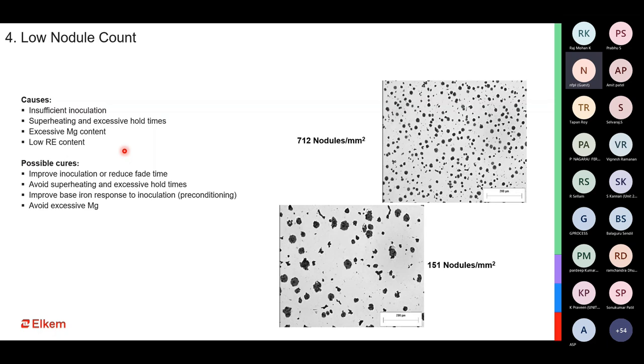And when you do not create enough nucleating sites, you eventually reduce the number of nodules in the system. And let me tell you one more thing, that when we have poor nodule count, it also means that we in general have a very poor nodularity, because larger the nodule count means smaller the nodule size, and smaller the nodule size means better is the tendency for the nodule to keep or hold its shape, the spherical shape. And thereby, as you keep reducing the count, you keep increasing the graphite present in one of the nodules, and thereby it becomes very difficult for those nodules to hold its shape of a sphere.